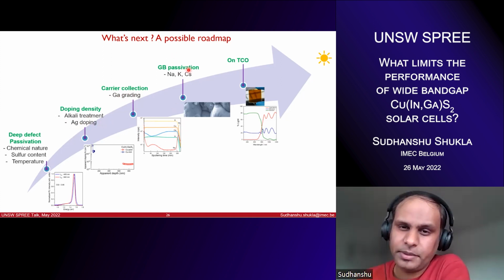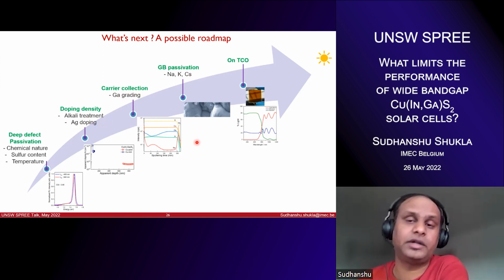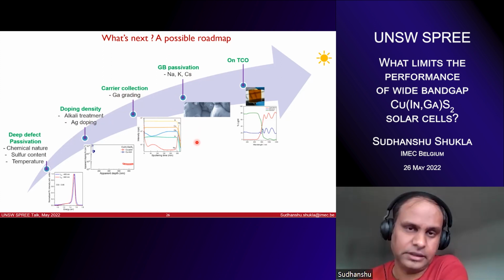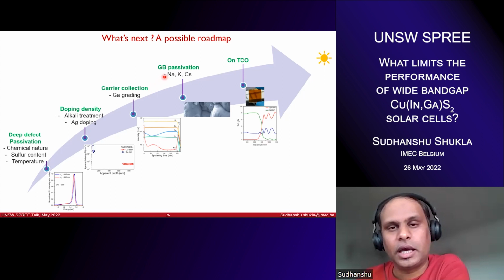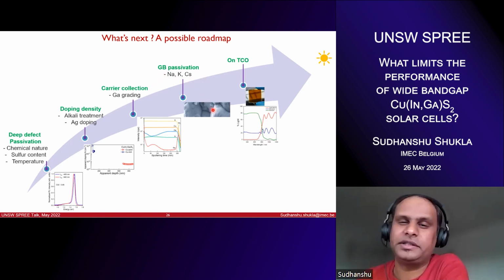And then grain boundary passivation. So we are getting some hint that the grain boundaries are actually lossy from the CL studies, and we are doing more extensive studies on that. And you will soon probably read something about it. And there also you can think of something like sodium, potassium, or cesium passivation, like alkali passivation of the grain boundaries.